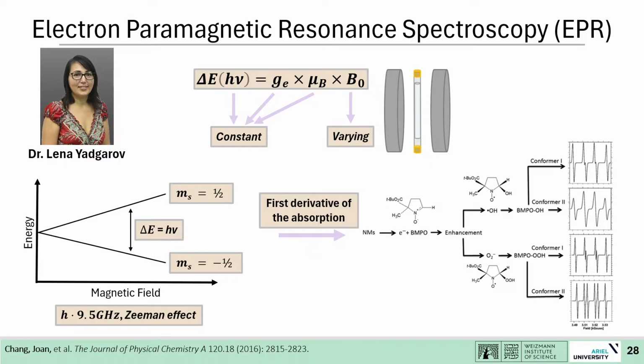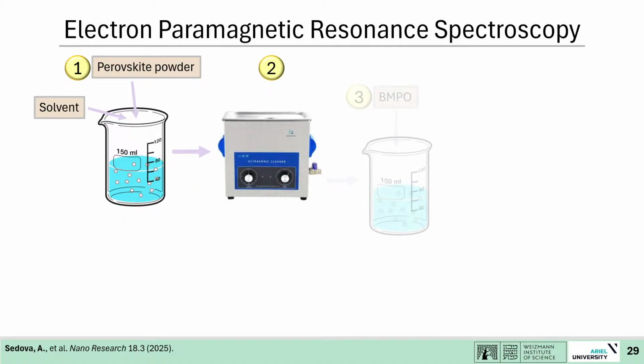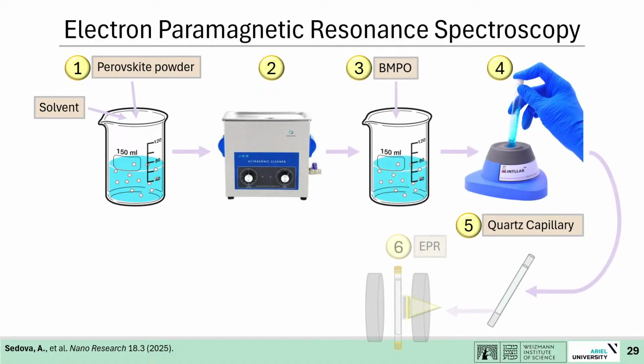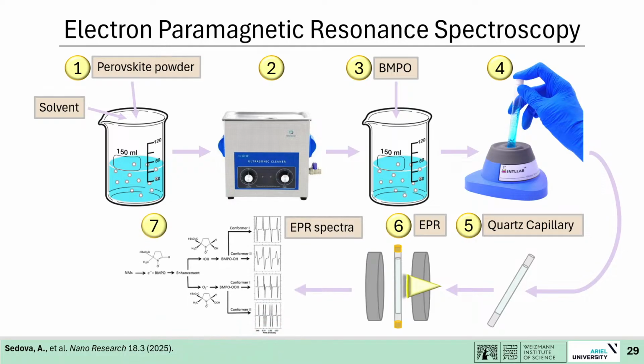We were working with the spin trap called BMPO that can trap radicals such as hydroxyl and superoxide, and the spectrum of it is known. So any change in this spectrum is visible. The preparation of the samples for the measurements is frankly simple. We were studying degradation of perovskites. So first we dispersed our material in a solvent to which we add BMPO. We place it into a quartz capillary, and at this stage we could illuminate the material with light in order to generate electrons, so that our semiconducting material will be contributing electrons to the system.